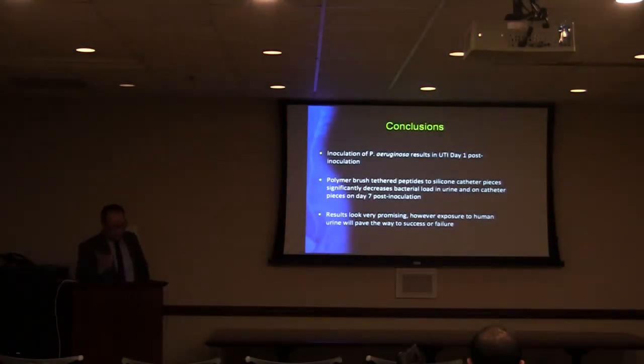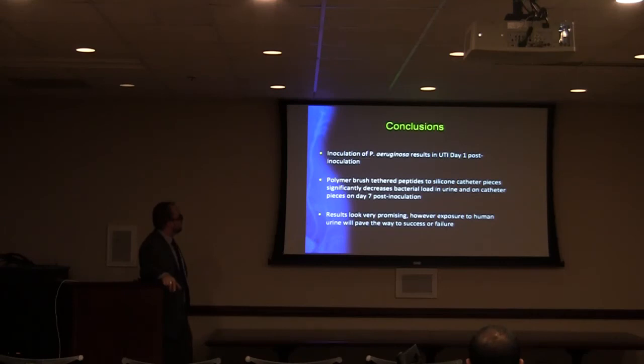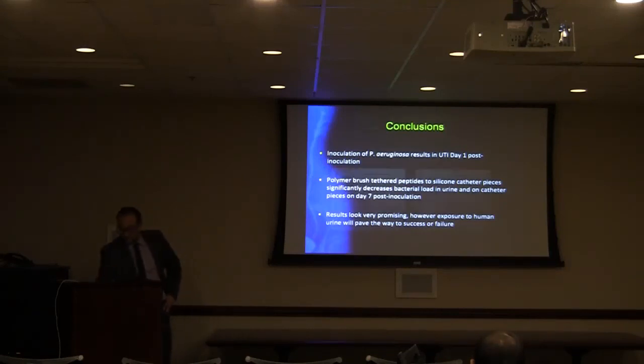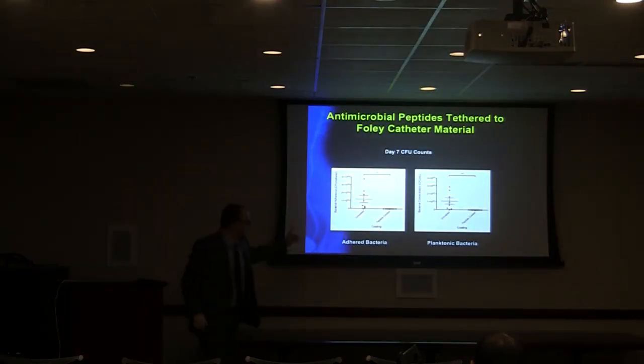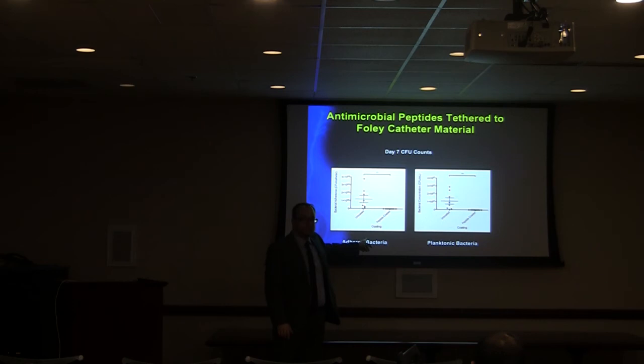So, to conclude, we did have an infection at day 1, which is good. Everything was good, baseline. And the polymer brush tethered peptides did significantly decrease bacterial load. That was point 2. It was also on the surface, so on the catheter piece itself, as well as in the urine.